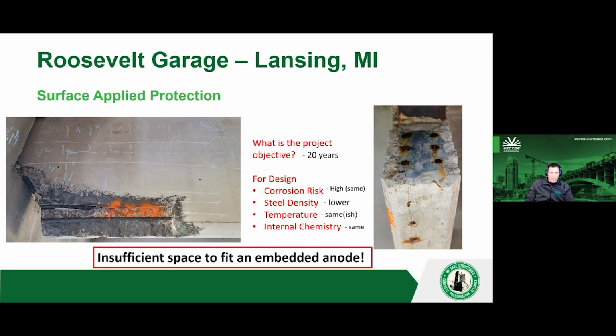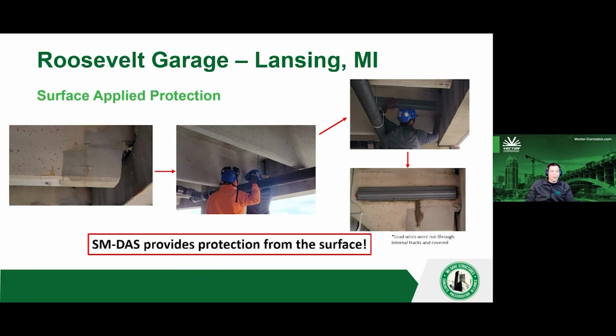One of the considerations here is that there's insufficient space to fit an embedded anode. Because even if you did want to fully open this area up, you're going to release all the tension from the strands, and then they're not doing you too much good. So they want to keep all of that in place, but there's not enough room to fit an embedded anode because this is such a small profile, this precast double T stem. So what could they do? And I've alluded to it, a surface applied approach.